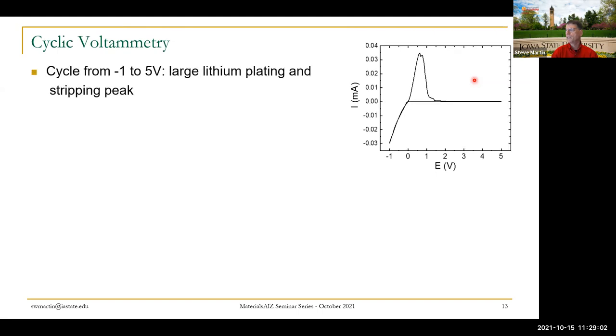So let's look at some of the electrochemical behaviors of these glasses. To remind you, here's a cyclic voltammetry where one side of the glass is lithium metal and the other side of the glass is stainless steel. Using that stainless steel, we can apply a positive voltage. If we just put lithium metal on both sides, we're stuck at 0 volts versus lithium. But by having this stainless steel electrode, we can pull that electrode to positive oxidizing potentials and kind of imitate what a cathode would be doing to the glass.